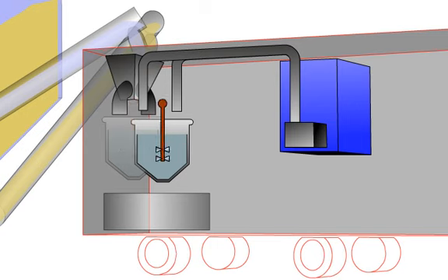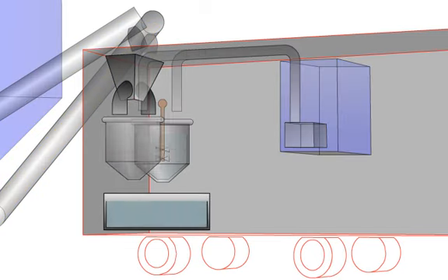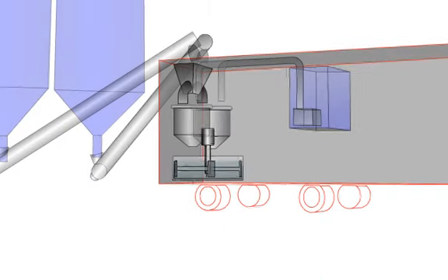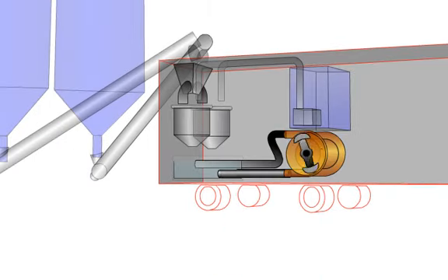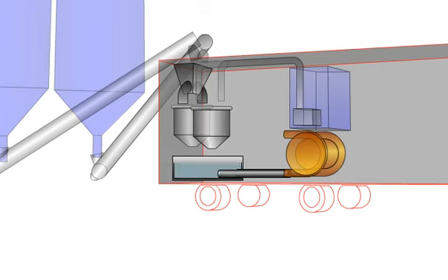The mixed slurry is dropped into a buffer tank, which is located under the mixers and is equipped with a built-in agitator to prevent segregation of the slurry. From the buffer tank, the slurry is drawn through twin peristaltic pumps at a rate preset from the control panel. The pump speed can be adjusted for any desired production rate of foam concrete, up to the maximum of slurry production. The pump speed, or extraction rate of slurry from the buffer tank, controls the batching of the slurry.